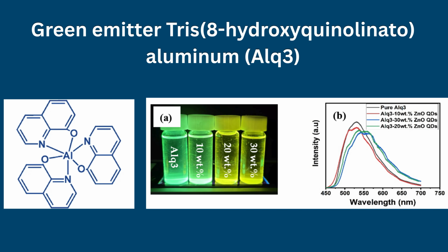Early devices employed tris(8-hydroxyquinoline)aluminum, Alq3, achieving EQEs of approximately 1% with emission around 550 nanometers.